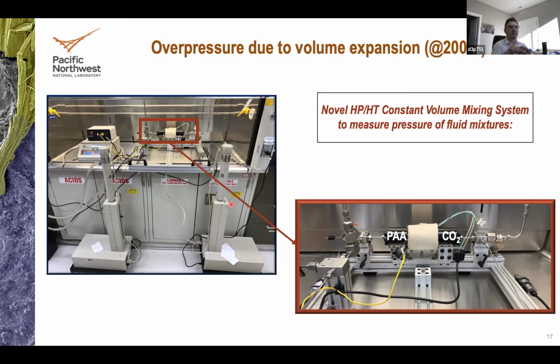So this is, I think, a 40 milliliter vessel. It's a flow reactor, a very simple reactor, but it has a key component. It has inside a piston that separates two volumes. We can inject polymer solution or water on one side, and we can inject CO2 on the other side. They will not mix, so this is a constant volume cell. They will not mix unless I move the piston.